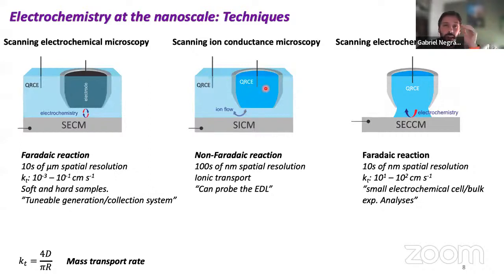But more importantly, if I bring that really close to the surface, a few nanometers, tens of nanometers from the surface, now the double layer that's developed on a substrate, and any material in solution will develop a double layer, starts to impact the ion transport because the gap's so close that the ions cannot move freely in and out of this pipette because they're going to sense the double layer somehow. They're going to be disturbed. The mass transport is going to be changed by the double layer, and I can use that to probe the surface charge. So SICM is characterized in that it probes ionic concentration or conductivity in solution, and we can use it to probe the double layer and the double layer characteristics.